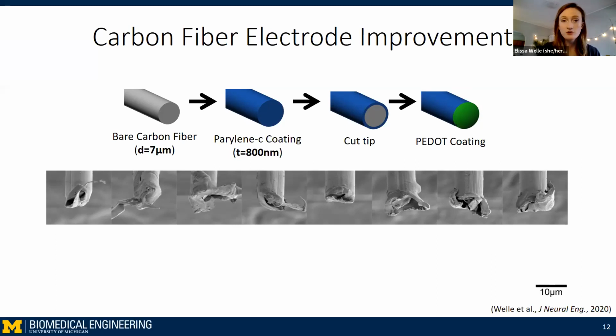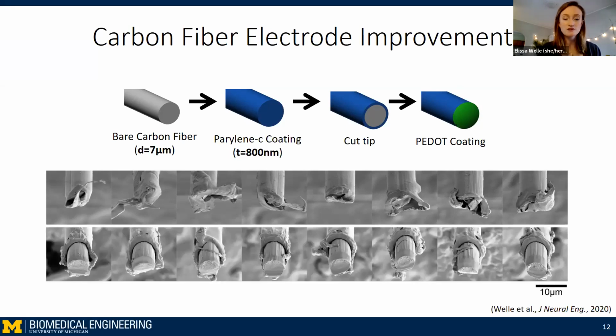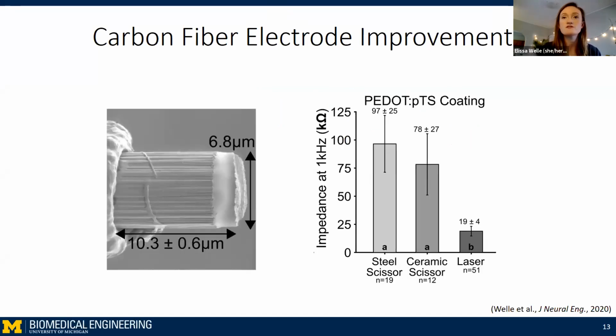So we developed a method using blasts from a green light laser to expose the tip of the carbon fiber and peel back some of the parylene to create a more consistent electrode site. You can see some SEMs here of the electrode with a more consistent, less variable exposed carbon. The laser exposes roughly 10 microns of carbon from the tip to create a surface area of about 250 square microns. And then the impedance drops down to 20 kilo ohms when coated with PEDOT. So we've created an electrode that does have a greater surface area than previously seen, but these dimensions are still on par with an ideal point source electrode. In fact, the size of a neuron in layer 5 of a rat motor cortex is roughly 15 microns. So we're still well below the size of a neuron, and we've created a subneuronally sized electrode with very low impedance.